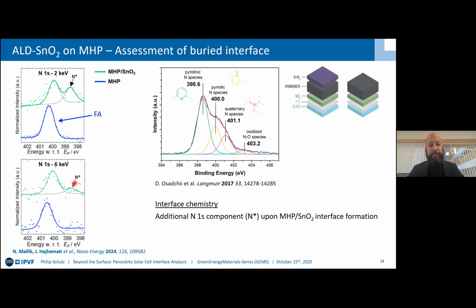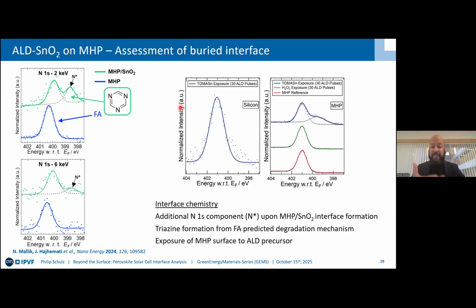We went into the literature to understand what this N star corresponds to. Pyridinic nitrogen species made sense, and then once you take additional references or corollary measurements, for instance FTIR measurements that we didn't do but others did, we were able to conclude that very likely we form triazine, which is a classical degradation product of formamidinium containing perovskite, really focused at the interface.